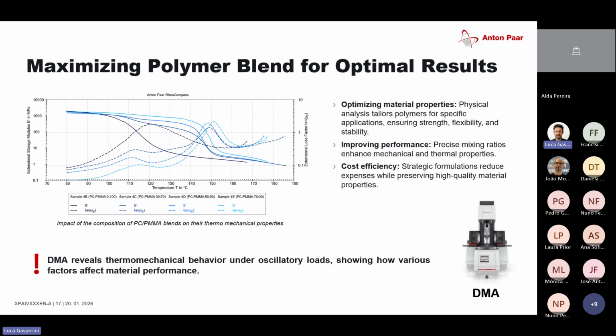For PC PMMA, I brought a DMA example with me just to showcase why this is of interest. If you mix PC and PMMA, the dark line corresponds only to PMMA. As you can see here, we only take a look at the storage modulus. At around 115 degrees, you see a drop here. The sample has its glass transition temperature here. If I take a look at the loss factor, we have one peak here, which tells me the glass transition temperature is there, and we only have one because there's only a single peak. Now if I mix PC with PMMA, which is the light blue line, what we expect happens: the glass transition temperature is much higher because of the PC part of the mixture.